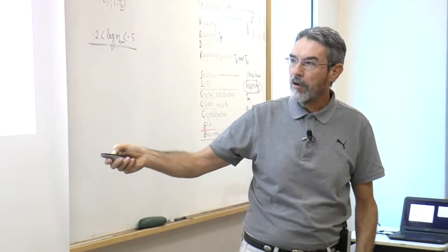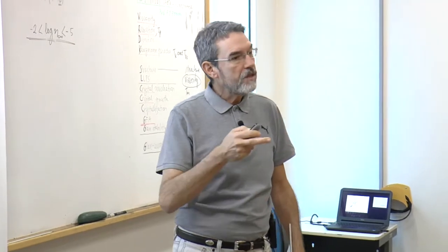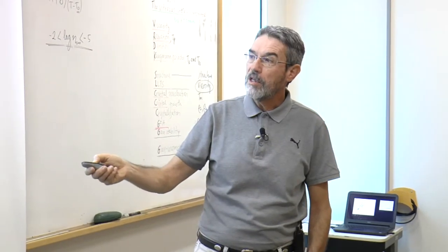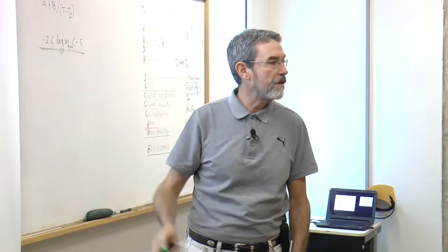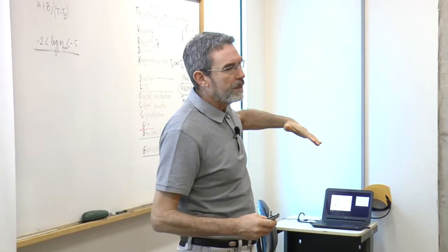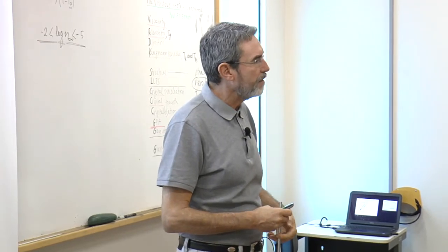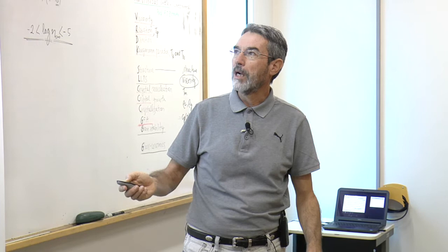So you'll be calculating the configuration entropy for your glass. You just need calorimetric data. And then you fit the viscosity of your glass using this type of curve here. Log of viscosity versus 1 over T delta S. And it should give a straight line. So this is the third fit, because last week you worked with a Vogel-Fulcher equation and with the other equation. This is the third equation you're going to use to fit the viscosity of your glass, right? Second homework.